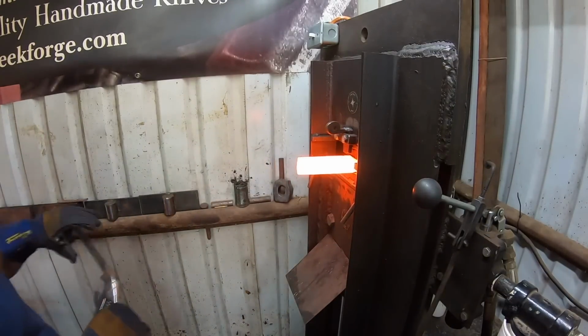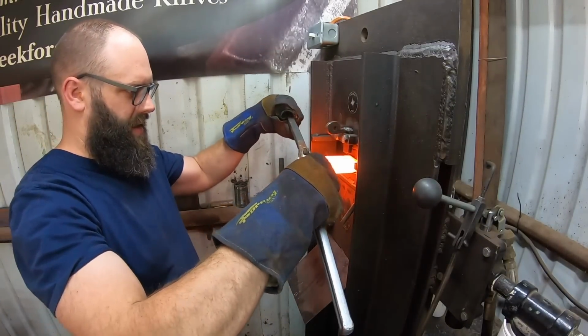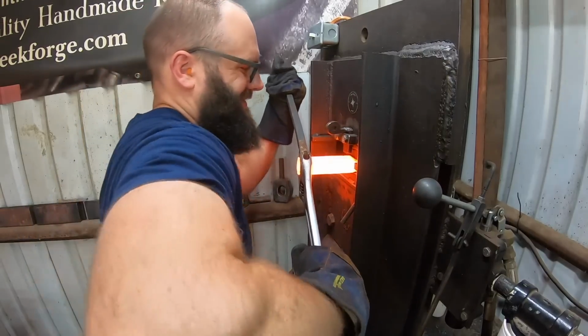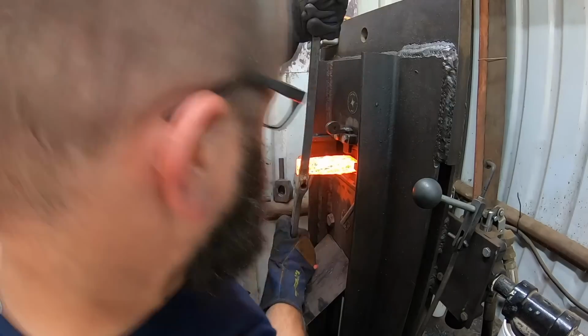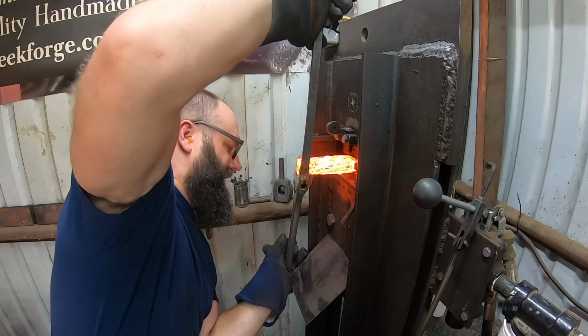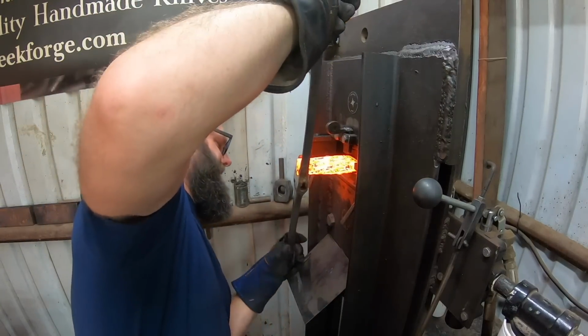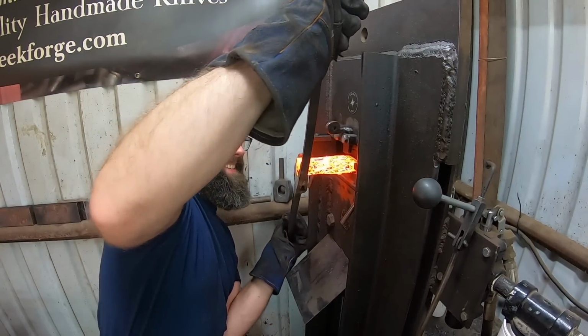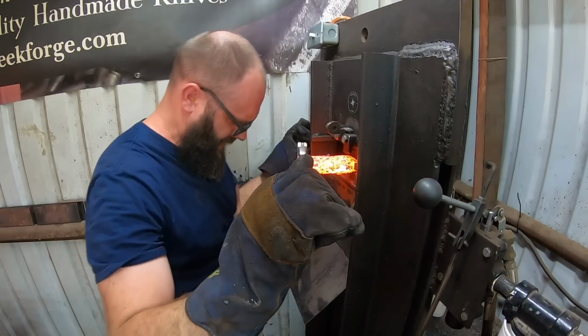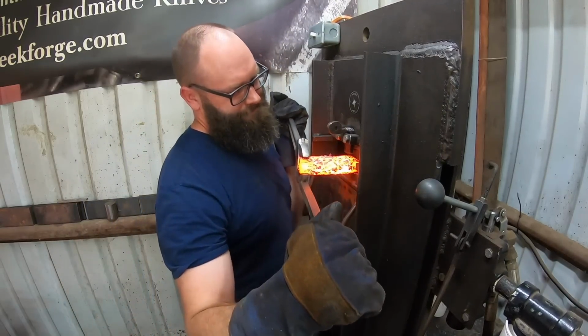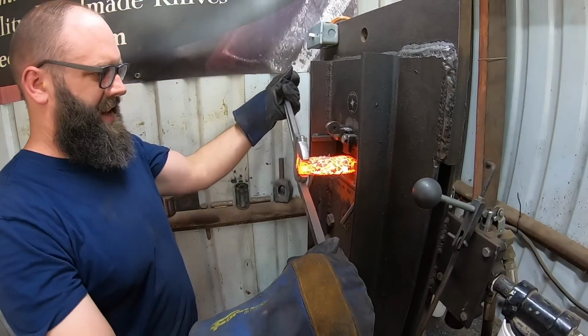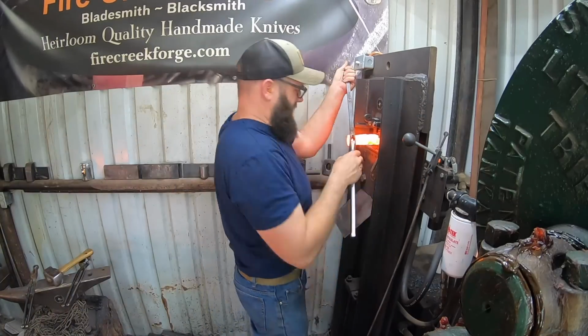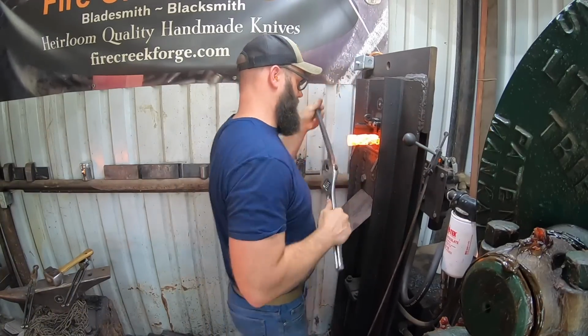And the next step, drum roll please, is to twist the billet. Now this proved to be a bit of a challenge due to the size of the billet, the cross section, a little bit thicker than you want to be twisting by hand, but also the fact that it was so close to the forging press frame here. I didn't have any clearance to work with, and those two things combined made it pretty tough to get twisted.